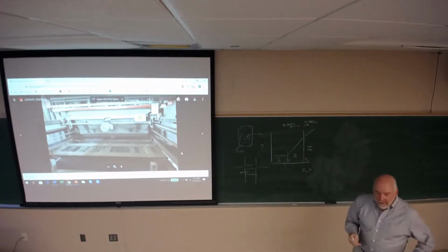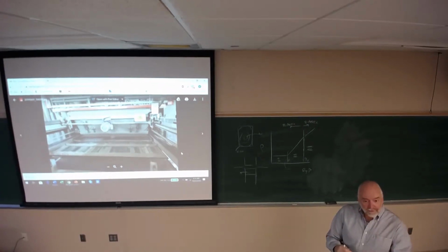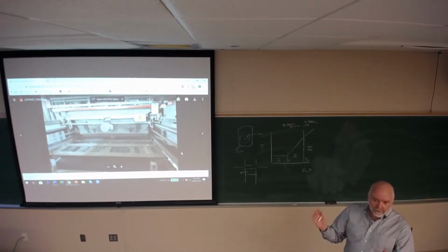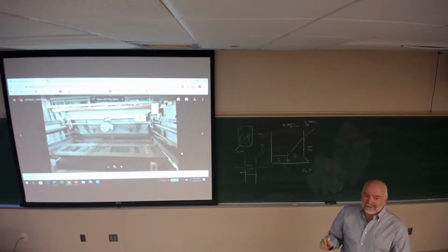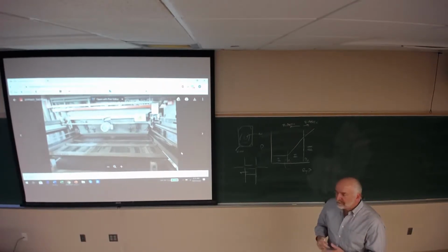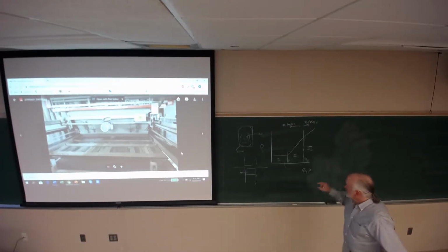So he actually had his granule in there, and then he sheared that material in the shear cell. Under load, then he increased the load. He did a really brilliant job. He counterbalanced the arm so there was no friction in the system. I mean, truly spectacular piece of work, right? He spent hours figuring this out, and he generated this compaction diagram. He's loading this material, and he's measuring then the compaction by measuring the thickness.